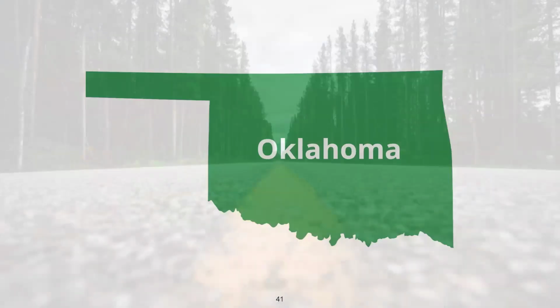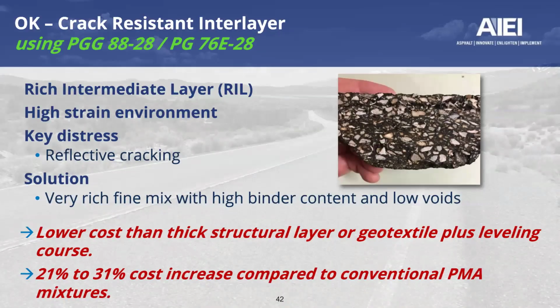Moving on to yet another O state, this time Oklahoma, where they are using these, as Johnny already mentioned, commonly as a rich intermediate layer in very high strain environments. What they are looking to address is reflective cracking. They believe that the solution that they're finding success with is this very rich, fine mixture designed to low air voids with a high binder content.